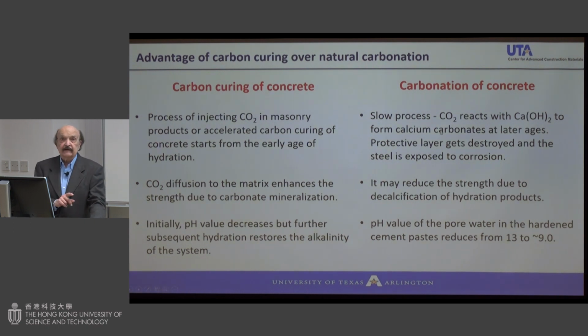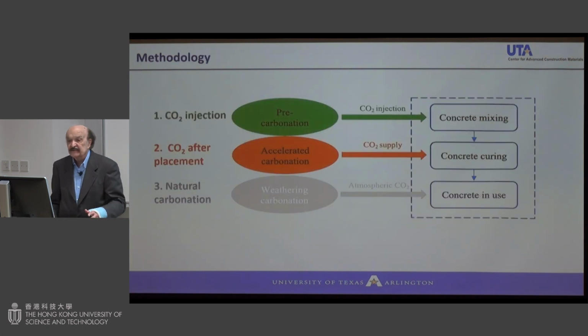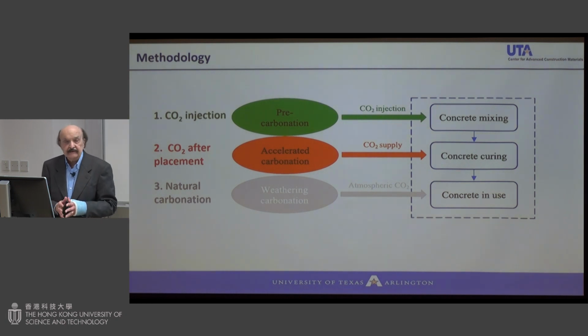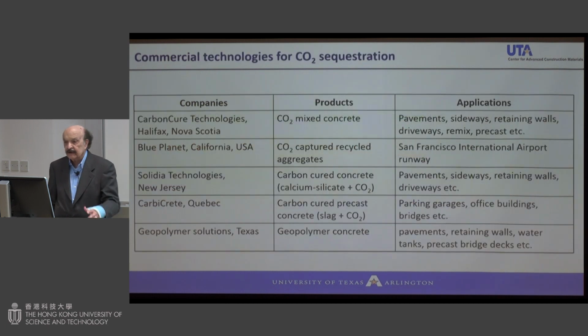Now, carbon curing is different from carbonation. You do it at a very early age. The diffusion of CO2 is enhanced because of mineralization, which makes the material strong. Although initially the pH value may go down, afterwards the alkalinity is restored. So the issues of carbon curing are different from carbonation. There are many ways you can inject CO2: during mixing or after placement, which is what we call concrete curing, and I'm going to emphasize that more, and obviously natural carbonation that I mentioned already.